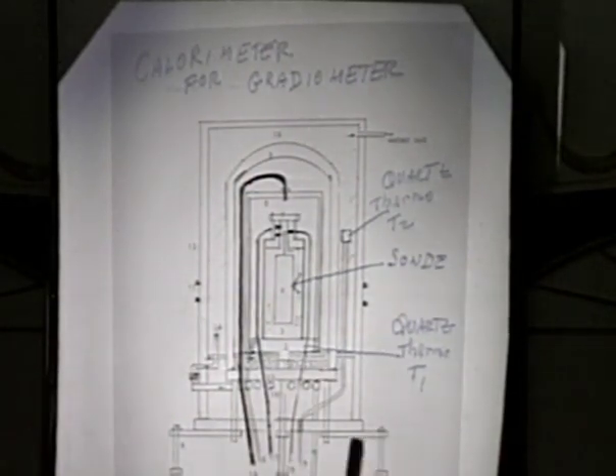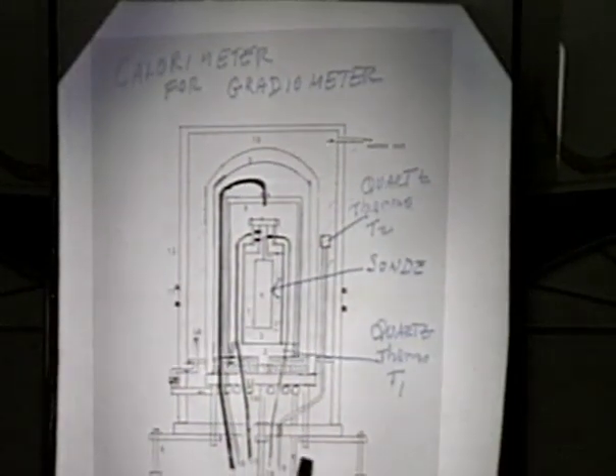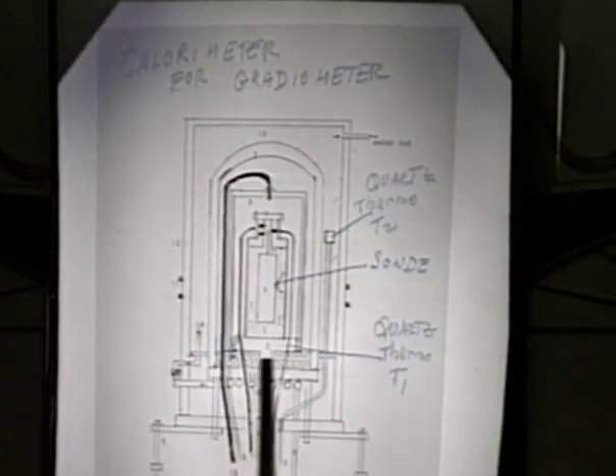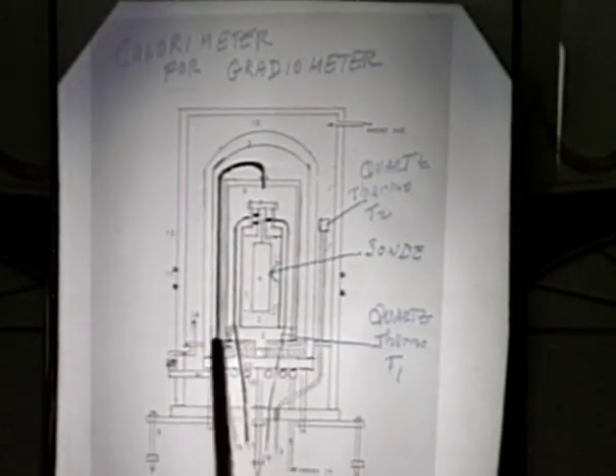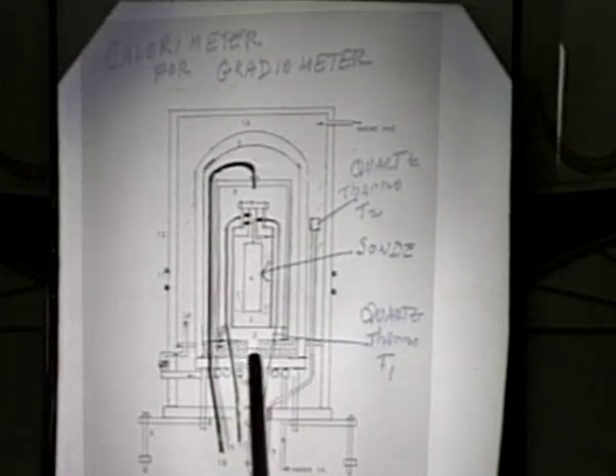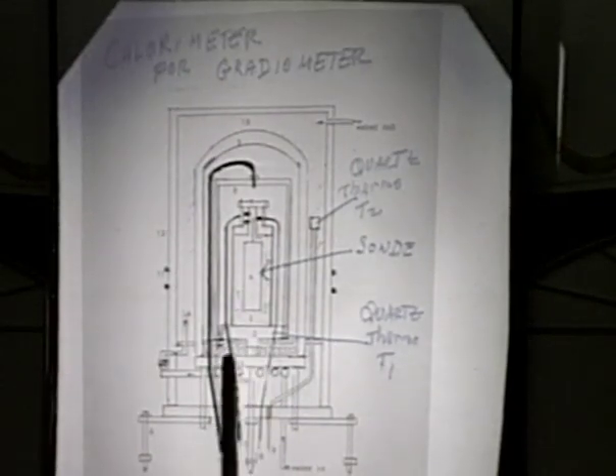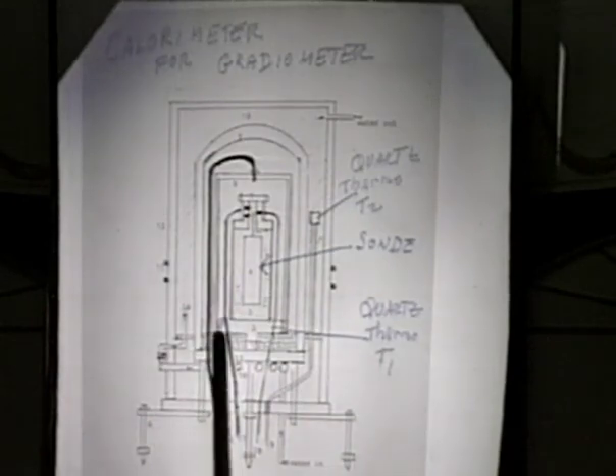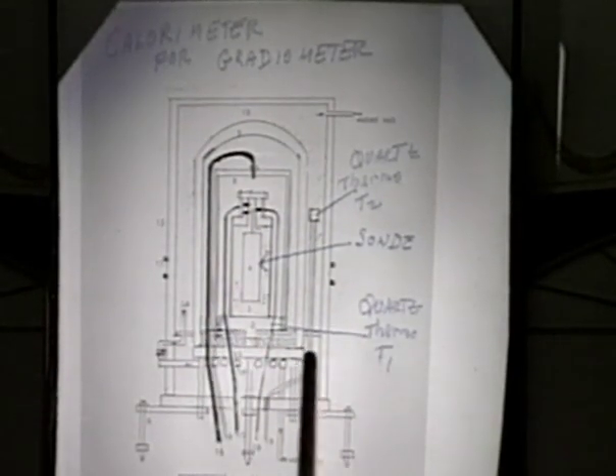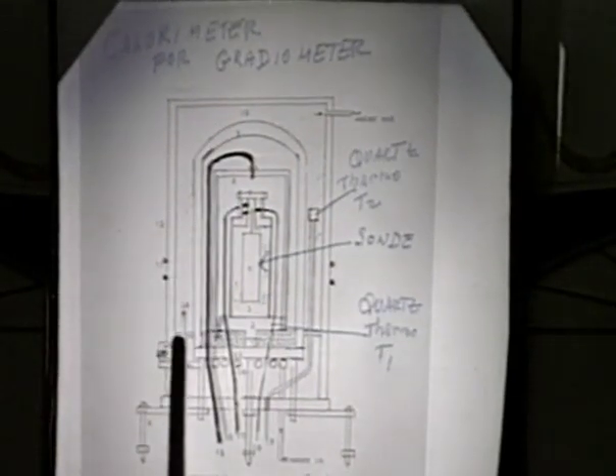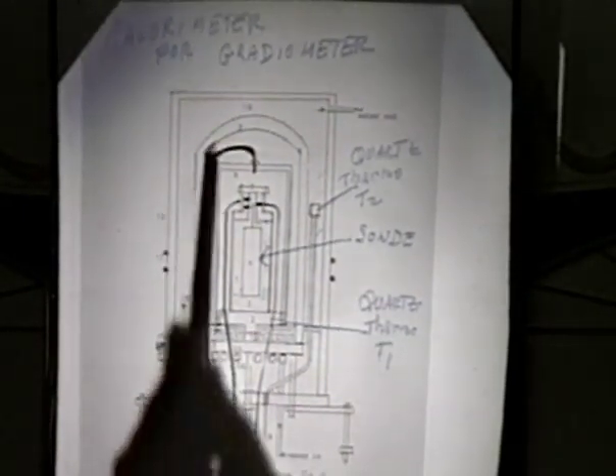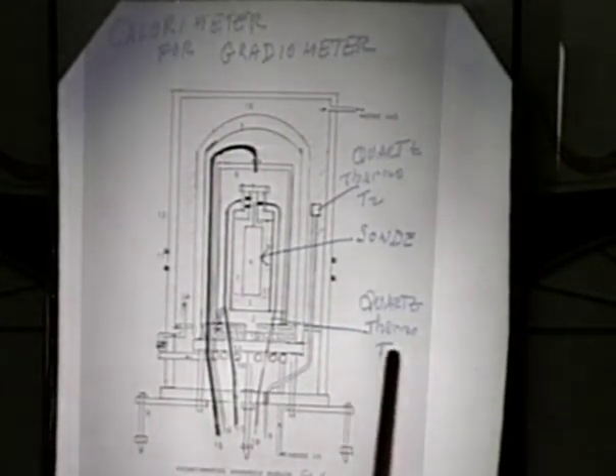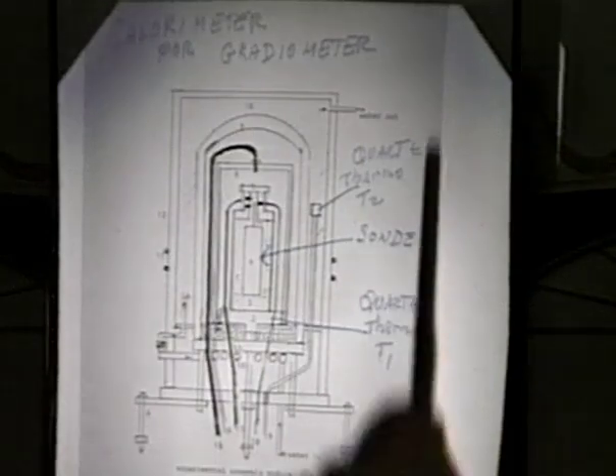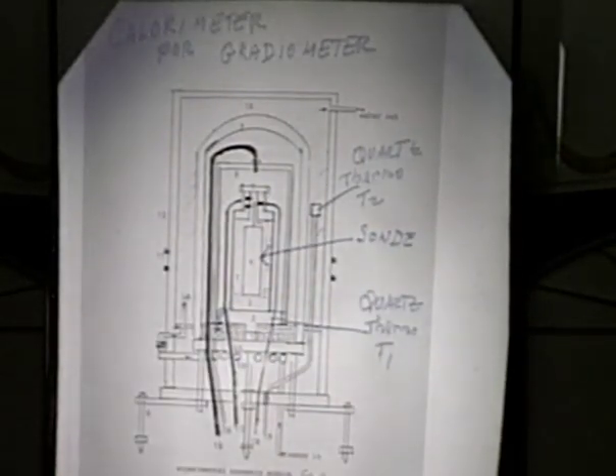The calorimeter essentially consisted of the container itself, an aluminum container with a heavy base, and this base was in contact with the thermoelectric element, and a quartz thermometer measured the temperature of the base. The calorimeter, the dewar, was surrounded by a water jacket circulated with thermally controlled water temperature, and then the whole device was insulated beyond that.